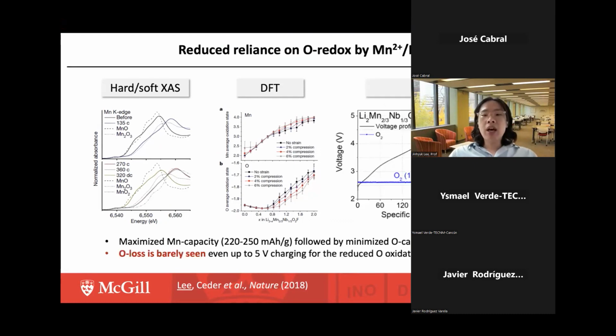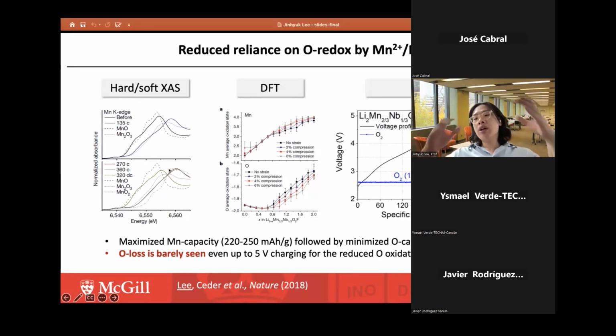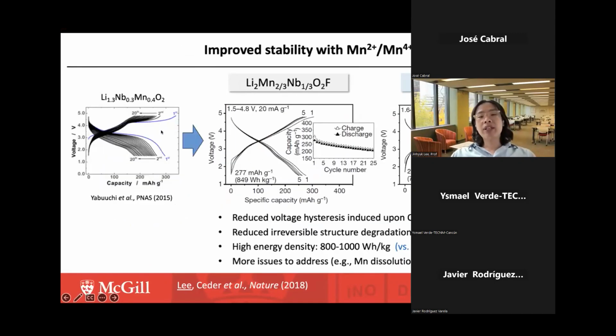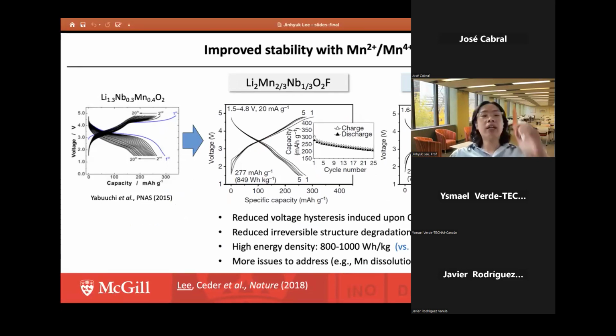Because of this, we found that even up to a charge of 5 volts, and you're looking at the right side, the gas evolution profile, there is a basically negligible amount of oxygen gas evolved from the structure. By the time this paper was published, this was a very interesting result. So this means that we can significantly reduce the oxygen redox related side reactions. And as a result, we can significantly improve the stability of this manganese-based DRX cathode material.